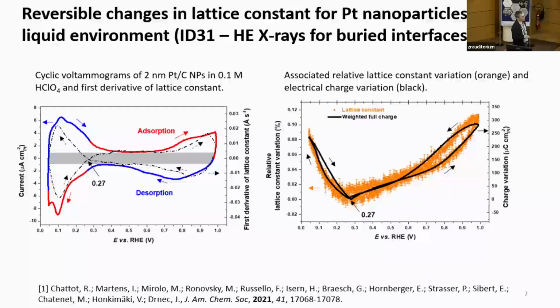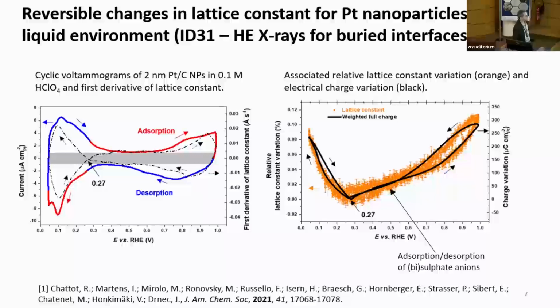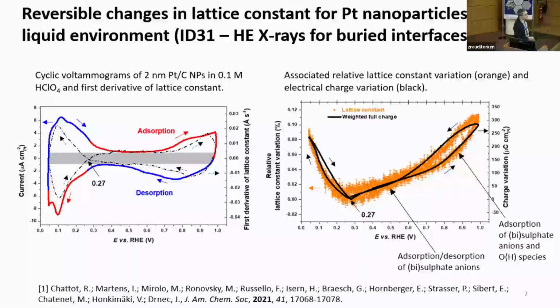So here in this region, you will get the adsorption of bisulfate anions, because those data have been done... So it will be perchloric here in this case. These data have been obtained in perchloric acid. And here you will probe the surface oxide. And here you will probe the hydrogen species that are on the surface. So from the slope, you can get insight into the nature of the species that are adsorbed on the surface.